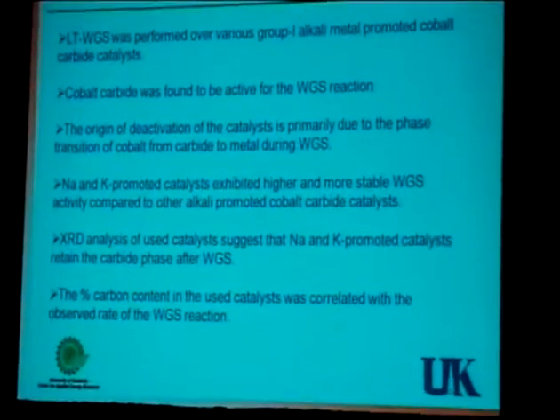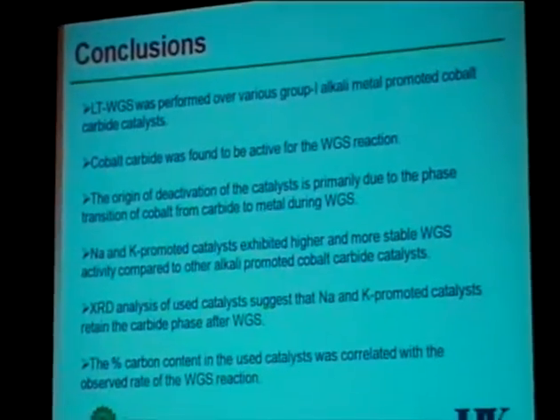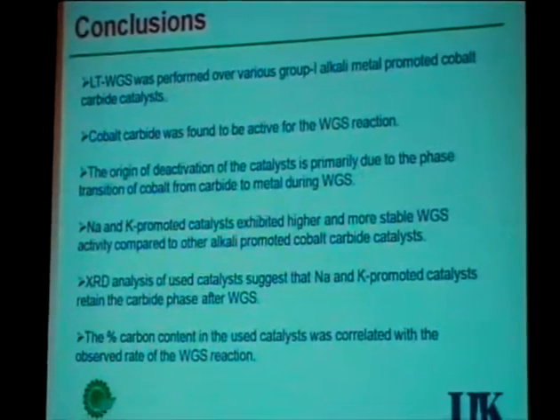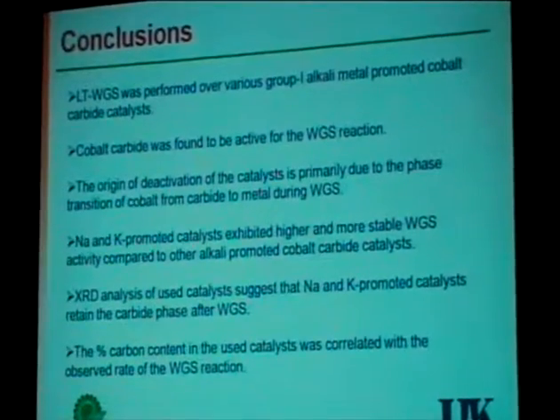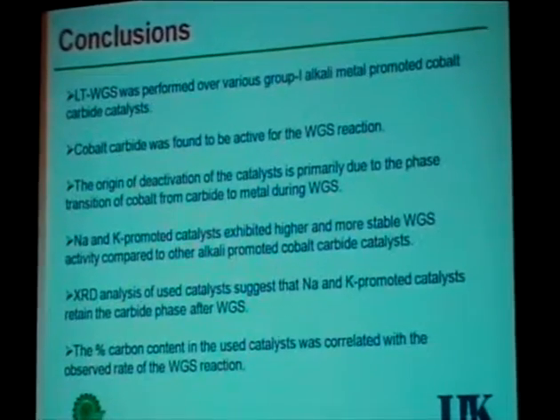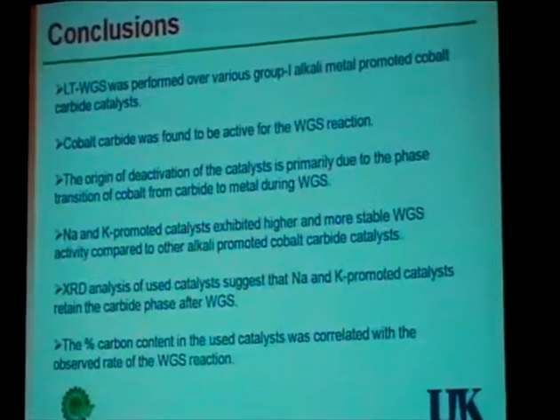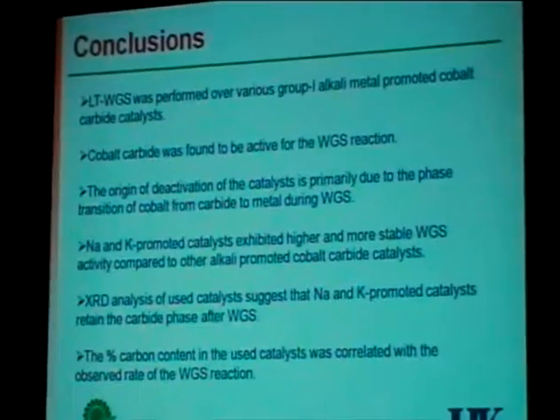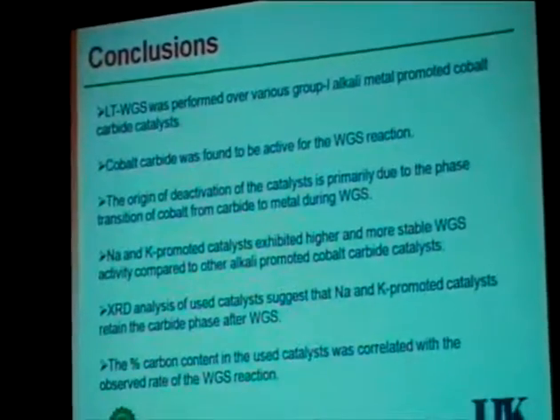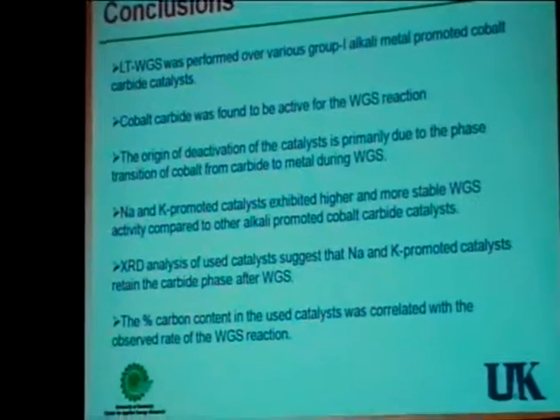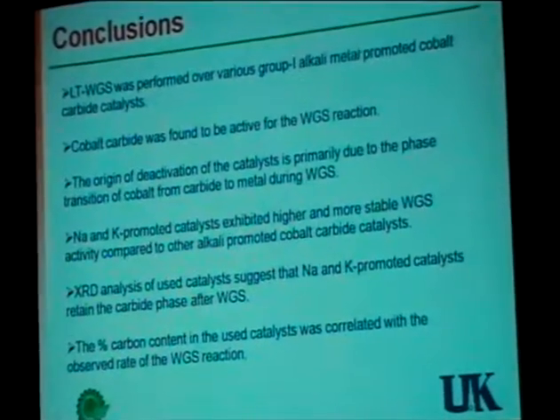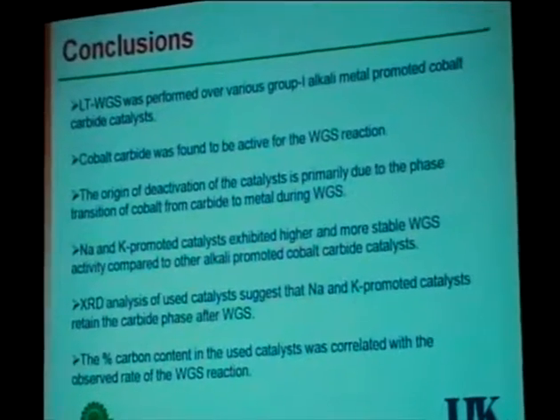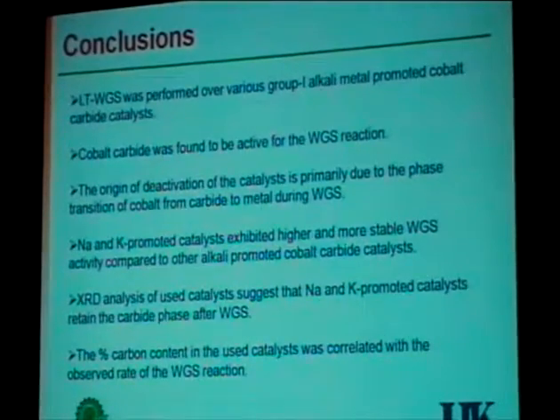And with this, I'd like to conclude that the cobalt carbide seems to be active for the low temperature water gas shift conditions. The origin of the deactivation of the cobalt carbide is primarily due to the phase transition from carbide to the metal phase, and sodium and potassium promoted catalysts exhibit higher activity compared to the other alkali promoted catalysts. The results are confirmed by the XRD, which shows that the sodium and potassium retain the carbide phase during the water gas shift. And finally, we made a comparison between the percentage of carbon content in the spent catalyst and the water gas shift rates we observed, and we have seen a linear correlation with the existing catalyst.